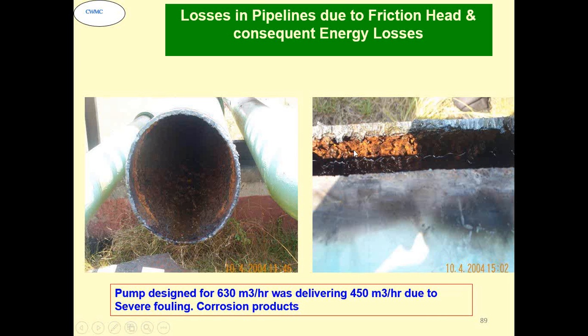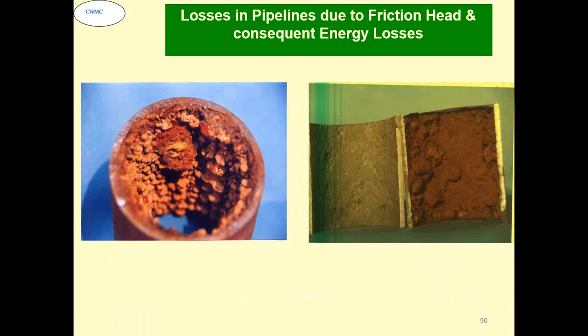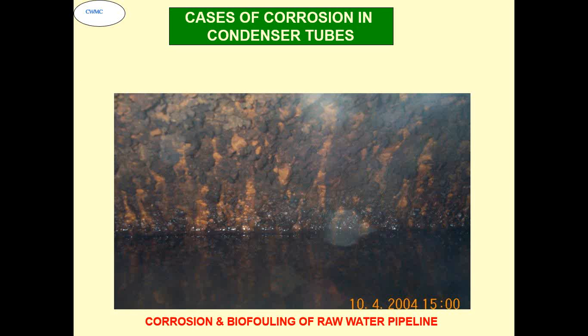The problem was resolved. This is the same station. You can see the raw water pipeline also so severely biofouled. Some more cases of biofouling. Again, the raw water pipeline of the same station, you can see what the condition is. We cut the pipe and we can see the biofouling inside. This water was only 10 ppm hardness, 10 ppm alkalinity, but such severe biofouling.